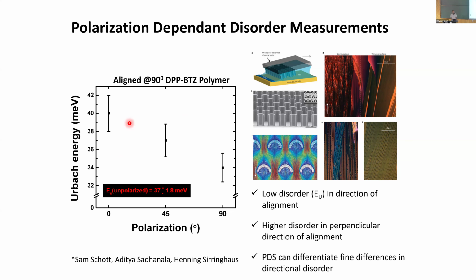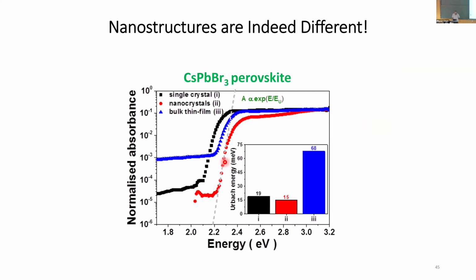If you polarize the light perpendicular to the sample, the disorder comes higher than the polarization along the growth direction, where the disorder is low. This shows that you have a material which is not isotropic in nature—you have a disorder that is anisotropic in a way. If you make devices out of it, you will see this performance difference. I won't bore you further with this.